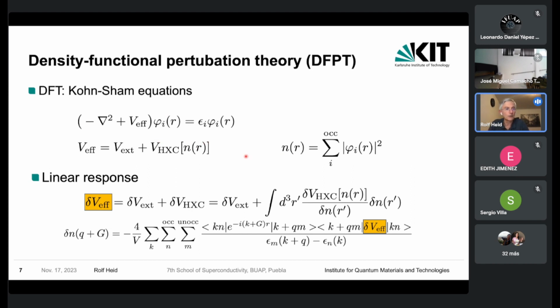If there is now a perturbation put on top of it, like, for example, introduced by a movement of an atom away from its rest position, then that induces a change in the external potential. But on the other hand, it also induces a change in the density of the system. And therefore, one gets an additional contribution to the change of this effective potential coming from this screening part. The change in the density itself can be calculated within a simple first-order perturbation expression, which also depends on the perturbation of the effective potential. And so we end up with a set of equations which have to be solved self-consistently. But that way, one gets information about the first-order change of the effective potential and of the density when we apply a perturbation, which, for example, is given by a movement of an atom.